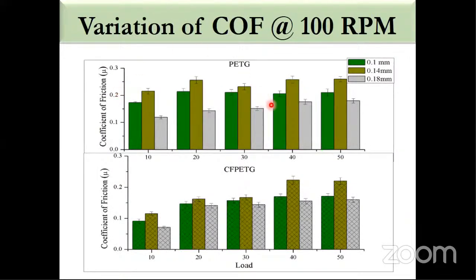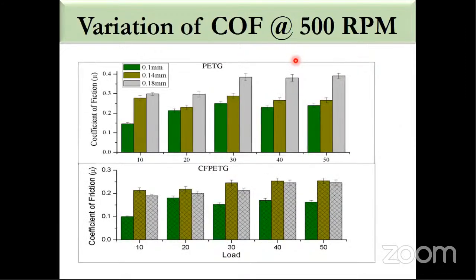And some of you must be knowing that carbon fiber, like graphite, is a very good solid lubricant. Carbon, because of its layered structure, has consecutive layers bonded by weak van der Waals forces. And when we use it in lubrication, it acts as a solid lubricant. And that was visible here, that when we tested these samples, the coefficient of friction reduced, and at different loads, in comparison to non-reinforced PETG, the coefficient of friction is lowered. That is one. And if you see at a higher RPM also, a similar behavior was observed, that the carbon fiber has a good role in reducing the coefficient of friction.